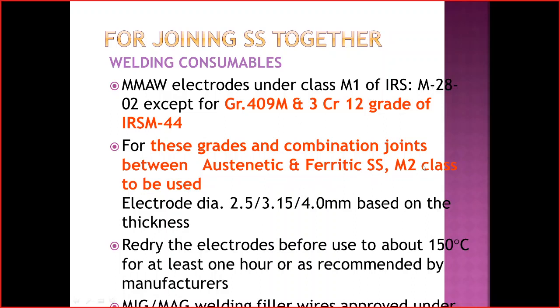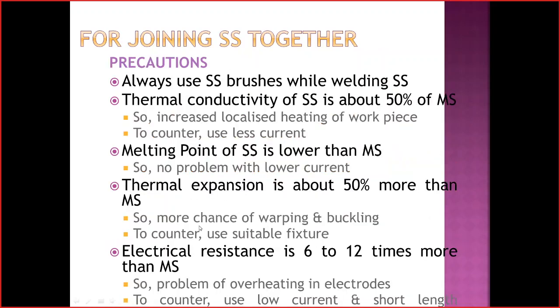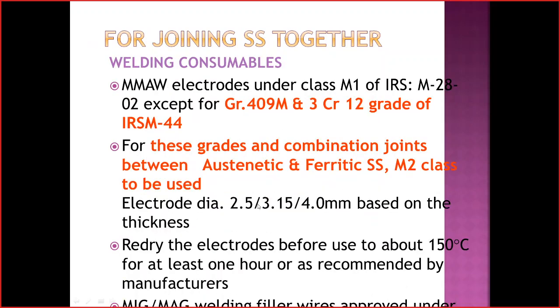The part also they will give clearly, you can understand. Electrodes are normally 2.5, 3.15, 4 mm; based on the thickness we can choose. Your CO2 wire is 1.2, 0.8. And re-dry the electrodes before using at 150 degrees centigrade for at least 1 hour. Okay, in the oven we have to keep our electrodes for 1 hour at a temperature of 150 degrees centigrade. This is recommended by the manufacturer.